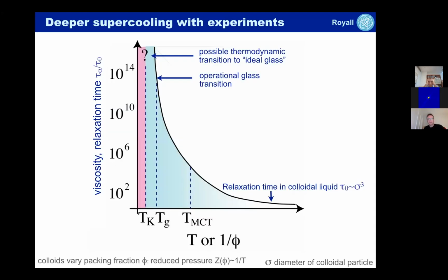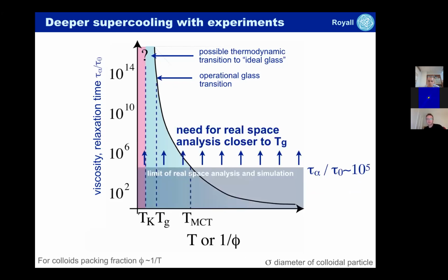So I've said that there's a 14 orders of magnitude change in the viscosity between a normal liquid and what we call the glass, or 14 orders of magnitude change in the relaxation time. So that operational glass transition I indicate here in this graph. Here I'm plotting the temperature. I reduce the temperature, the relaxation time increases. Now, what we can do with computer simulation is to get to where I've indicated here with the gray, and that takes us to something I've indicated as TMCT.